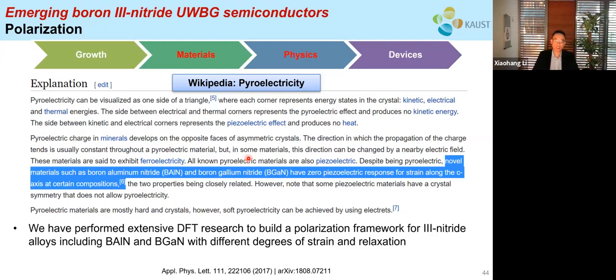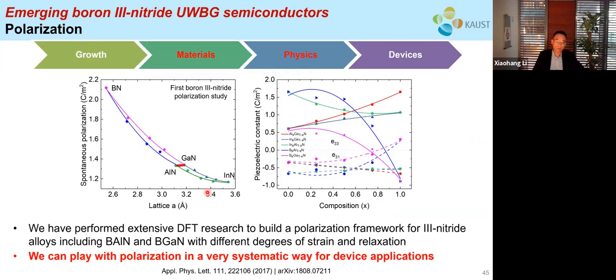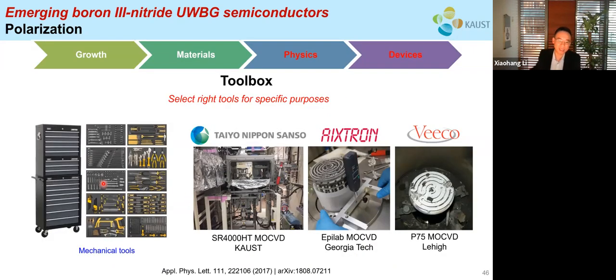One of our conclusions was cited by Wikipedia on its pyroelectricity webpage. So it says that some of the novel materials, such as boron aluminum nitride and boron gallium nitride, have some very interesting piezoelectric response under certain conditions. And more importantly, for electrical engineers, we can then play with the polarization in a very systematic way for device applications. I would like to use this mechanical toolbox as an analogy here.